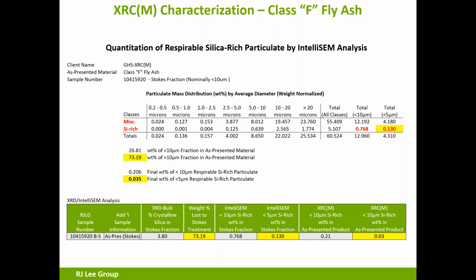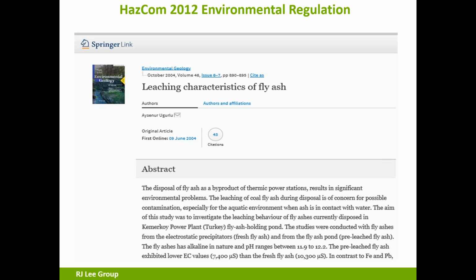Once we were done getting the 10 micron fraction, we then ran it through the IntelliSem, and you can see here that we got a total in the less than 5 of 0.13. When we back that into the amount of material that was lost, in other words, only 26% of the material is actually less than 10, 73% is greater than 10, we find out that we're at 0.035, which is clearing for GHS purposes. So 0.03 is our final value for the silica rich, which obviously is an ultra conservative approach to the crystalline silicas. We know if we go to Raman, it's going to be even lower than this. So this product is cleared. It did not clear Prop 65 because it didn't meet our threshold for non-detect, but it does clear GHS.